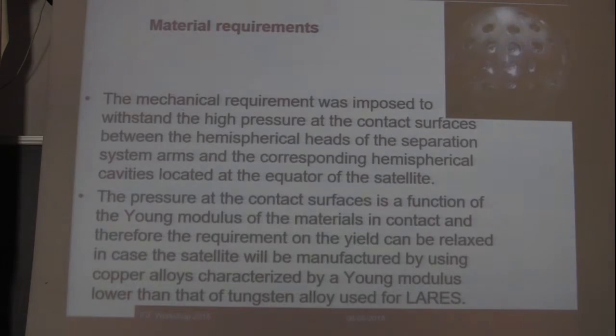To explain the problem, the mechanical requirement was imposed to withstand the high pressure at the contact surfaces between the hemispherical heads of the separation system and the hemispherical cavities located on the satellite. The pressure at the contact surfaces is a function of the Young modulus of the material selected. So if we select an alloy having a Young modulus lower than that of tungsten, the requirement concerning the yield stress will also be relaxed.